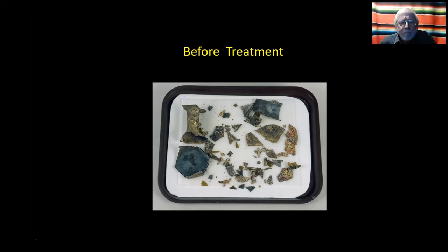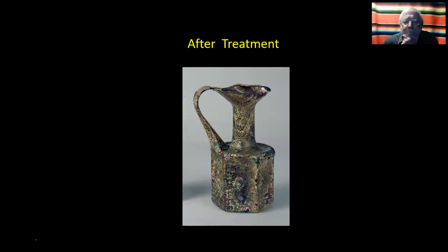You just join them. So you can only do a few pieces at a time because the adhesive will take up to 20 minutes, maybe an hour to set, even longer for thicker pieces. So you may need to just do two or three joins a day. So I did this piece and it took all of 6 hours. But it took 6 hours over a period of 3 months.